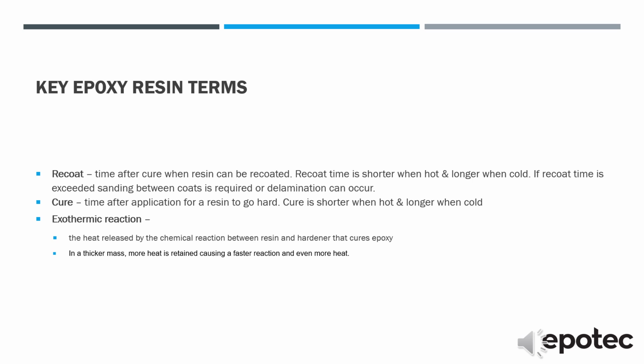Exothermic reaction is the heat released by the chemical reaction between resin and hardener that cures epoxy. Exothermic heat is produced by the chemical reaction that cures epoxy. The amount of heat produced depends on the thickness or exposed surface area of mixed epoxy. In a thicker mass, more heat is retained, causing a faster reaction and even more heat. The mixing container's shape and the mixed quantity have a great effect on this exothermic reaction. A contained mass of curing epoxy, 8 fluid ounces or more, in a plastic mixing cup can quickly generate enough heat to melt the cup and burn your skin.